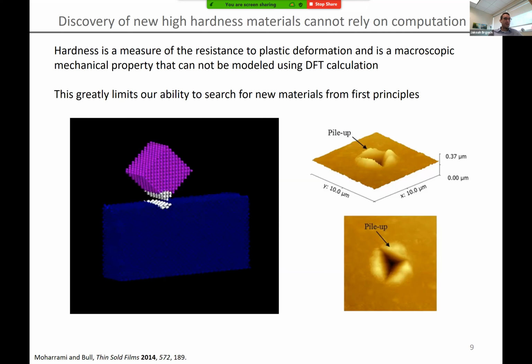The reason is shown very clearly in this molecular dynamics simulation. Here in blue is a copper block that contains a few 10,000 atoms and an indenter tip. What we're going to do within this molecular dynamics simulation is simply indent the copper block. And what you can see is the copper block is indented.